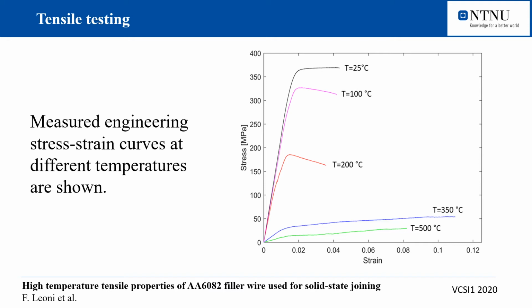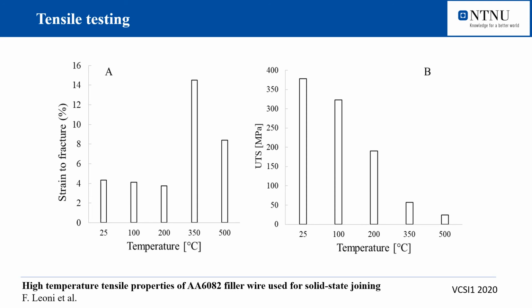In contrast, the fracture strain shows a different temperature response. Up to 200 degrees Celsius, the fracture strain appears to be essentially unaffected by an increase in the testing temperature. However, at 350 degrees, the material starts to behave more ductile before it becomes brittle again at a temperature of 500 degrees Celsius. From the measured curves, the data presented for the fracture strain and the ultimate tensile strength (UTS) have been extracted. In these two figures, it is possible to see the trend of the two parameters with respect to temperature.